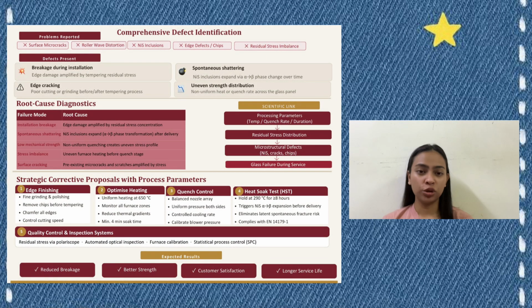Third is quench control, which is calibrating blower pressures for a perfectly balanced airflow. Fourth is the heat soak test. To stop spontaneous shattering, we cook the glass at 290 degrees Celsius for over 8 hours in the factory-like furnaces. They intentionally force those inclusions to expand and break defective panels before they reach a customer, complying with EN